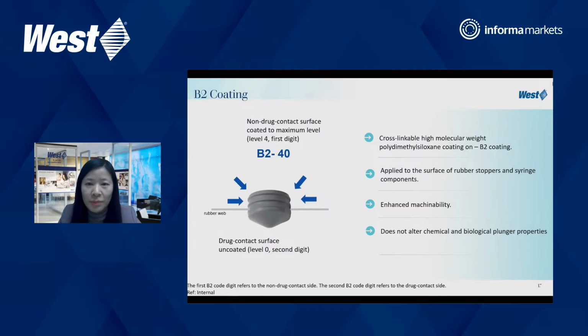Furthermore, for the plunger surface area without the FluoroTec film, we apply a B2 coating, which is a combination of high molecular weight silicones. After it is sprayed onto the surface of the elastomer, it is heated and UV cured to the surface of the elastomeric closures. It can help reduce the free silicone oil particles in the drug liquid. So the FluoroTec film, in combination with the B2 coating, provides lubricity without the need for free silicone oil, eliminating the potential source of particulate contamination, as mentioned. Next slide, please.